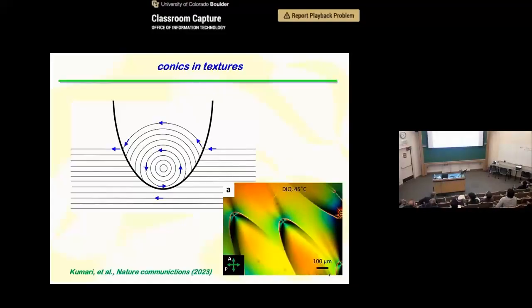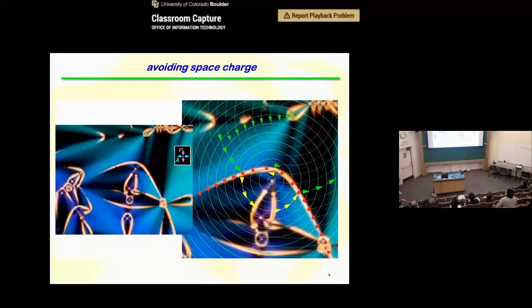and these are walls where the normal component of the polarization is continuous, but the tangential component changes sign. So there's no polarization on the walls. And these walls should have this width lambda that I calculated before, but typically they're way broader. So this is the kind of question that we're looking at, trying to understand, for example, the structure of the walls in these parabolic textures.